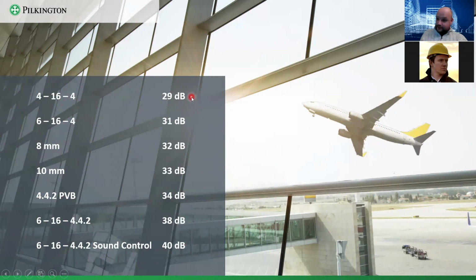And now overview this table and see how far we had to go from our 29 decibel to 40 decibel. So in order to make this IGunit block twice as much sound, we had to go from a very basic formula to quite a sophisticated one, meaning with laminated glass, thicker glass. So this one is much heavier and much costlier, but it blocks the sound twice better.